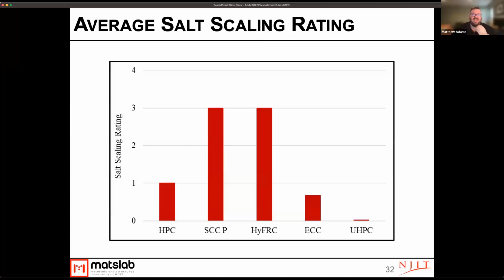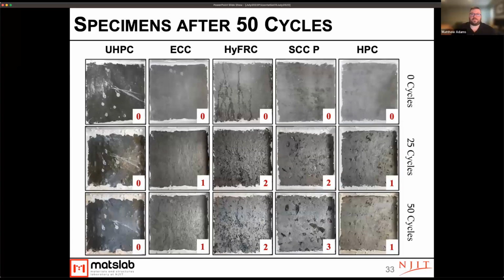And so what we saw was that the SCCP and the HyFRC both had the worst performance in terms of salt scaling. The HPC and ECC both had around a rating of 1, which is good, and the UHPC had essentially no damage noticed on it. Here's what the different samples look like over time. And so you can see once we get out to 50 cycles, so 50 cycles means you've put those chlorides on there and you've actually frozen it and thawed it 50 times with that ponding on there. And so you can start to see that surface damage build up. And particularly on the normal concrete, you typically get those pocks in the surface. That's very standard damage with salt scaling.